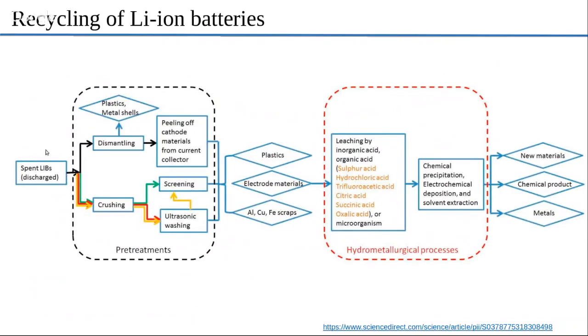You get the spent lithium-ion batteries. If it is significantly degraded, then you crush them such that all the parts come apart. Then the plastic shells, the metallic jacket and the cathode material, the current collectors, right? You get all that stuff and then whatever the important stuff that you need, the cathode, the nickel, the cobalt,